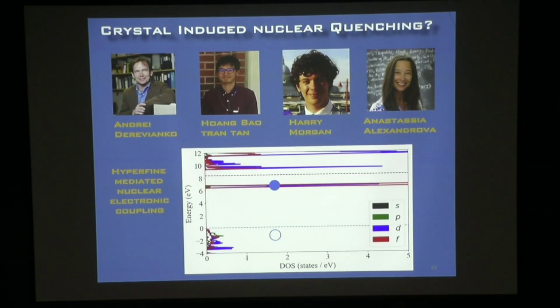And if it does that, this hole that's left behind will quickly quench to the top of the band. This happens in picoseconds because the phonons shoot out and this relaxes. On a longer time scale, nanoseconds or longer, maybe even seconds, this will then relax by photon emission. And if it does, it should make a red-shifted fluorescence because you have to excite from below the band to be resonant with this. So we said, okay, if this is true, let's go look for it.